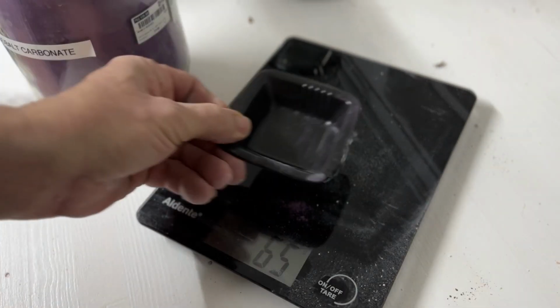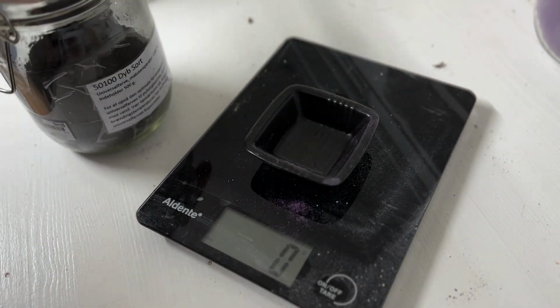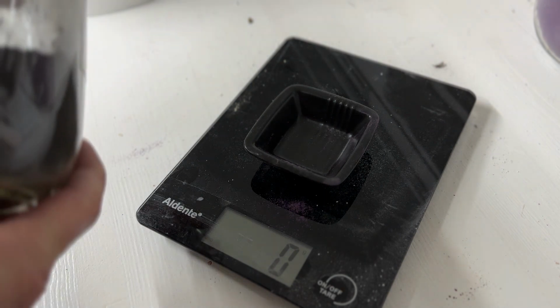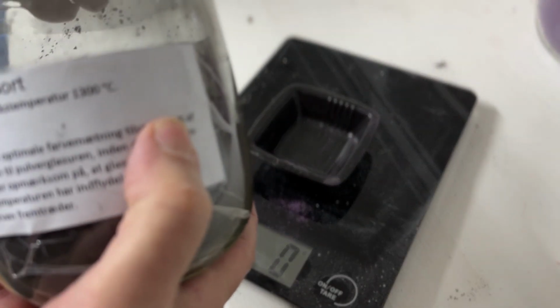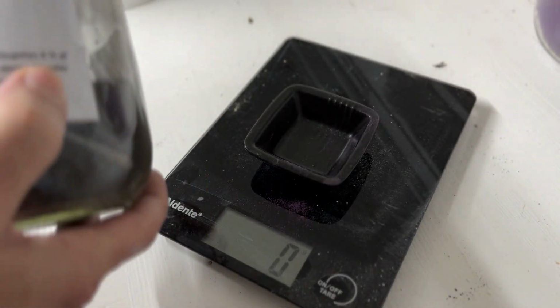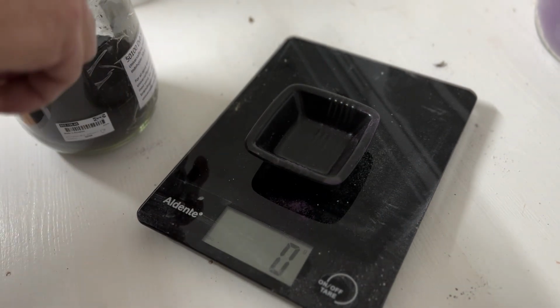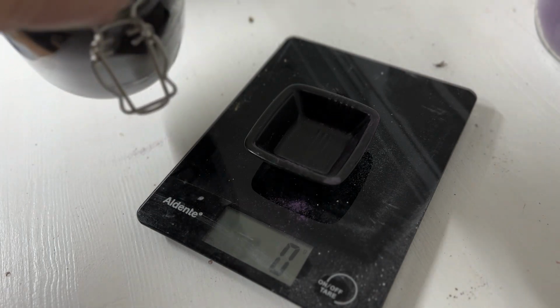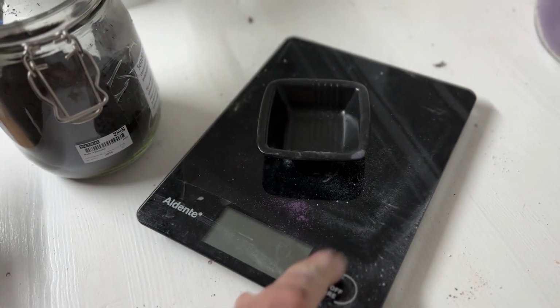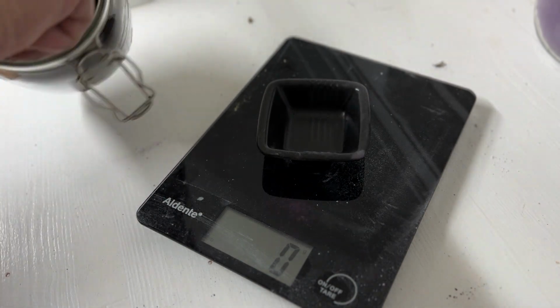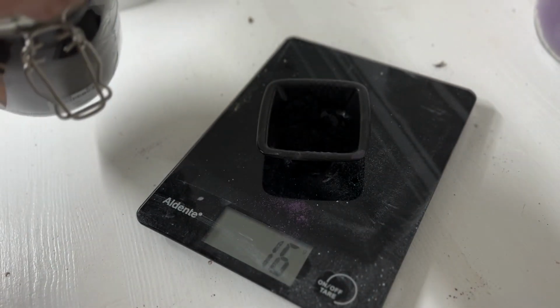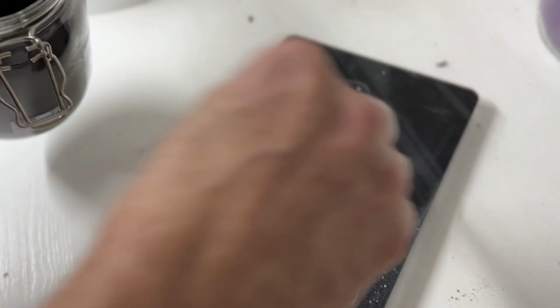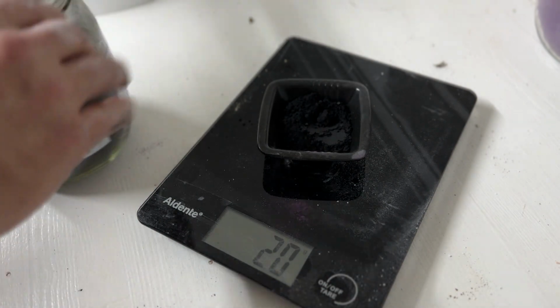I know I said that a few times now, but it really is. And now for the black. Usually I would use something like 4 or 5%. They say up to 6% of this, but that will turn things black. I don't want it black. So that's why I only said 0.5%, which I'm hoping would be sort of a gray. So 0.5 is 20 grams. So, oh, that was too much. It's actually not very much. I'll reset the scale. I think I need to change the battery. I definitely don't want to put too much of that in. So yeah, 20 grams. Exactly.